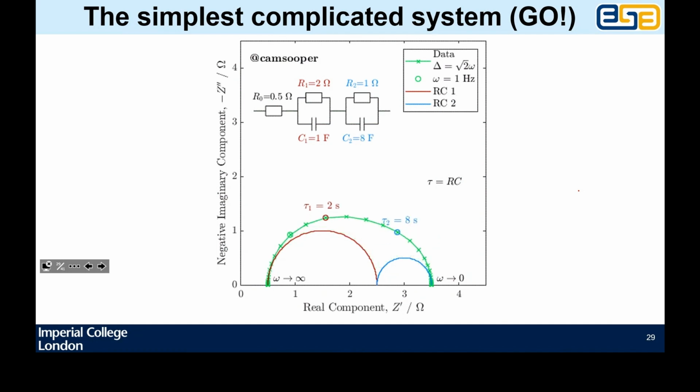And that's one of the big challenges with impedance spectroscopy. If your multiple processes have similar time constants, then everything gets jumbled up into a big blob. And that's when you start to think about Arrhenius laws, where you start thinking, okay, well, maybe I need to do this experiment again, but at a different temperature, or a different pressure, or a different concentration, such that I can shift the time constants of my processes away from each other and uncover a spectrum where the processes are nicely separated.